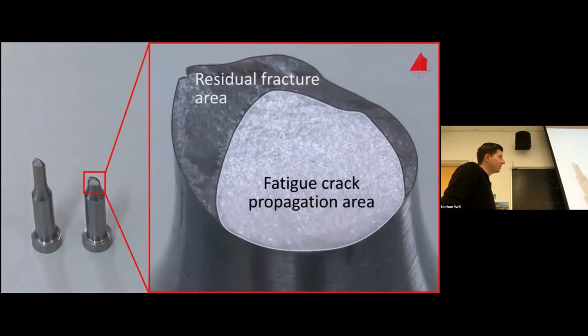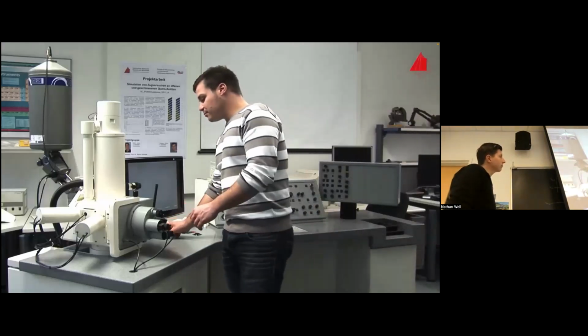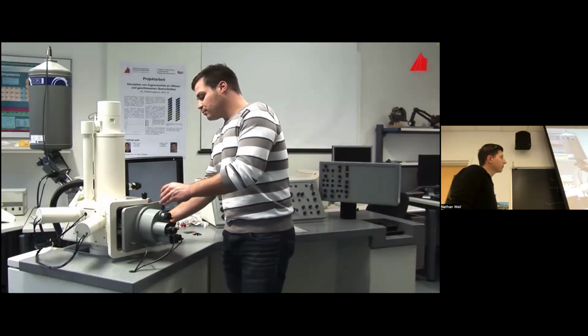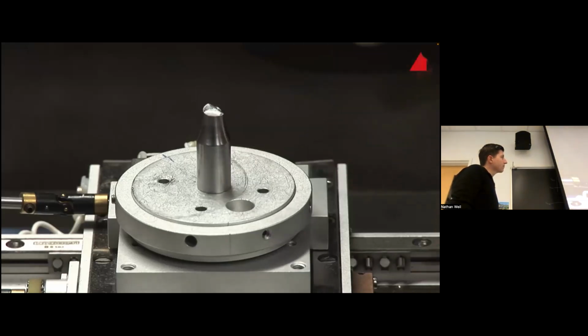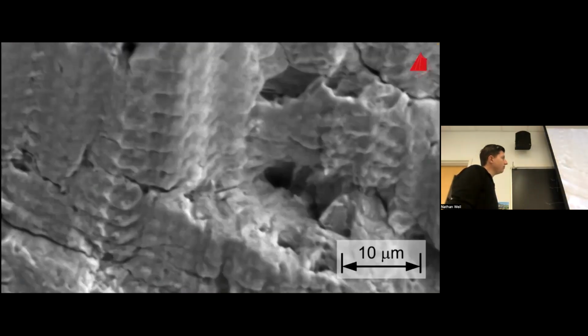The fatigue crack propagation area has developed during the cyclic growth of the fatigue cracks starting at the surface of the specimen. What does the fatigue crack propagation area look like at higher magnification? One of the fragments is carefully placed on the specimen stage of our scanning electron microscope. Now we can investigate the fatigue crack propagation area in detail. In some places, but not everywhere, parallel grooves and ridges can be seen, the so-called fatigue striations. Each groove and each ridge has been formed by an individual load cycle, a typical phenomenon.